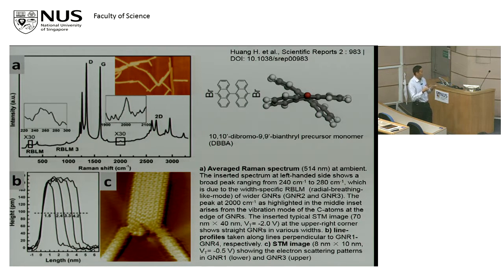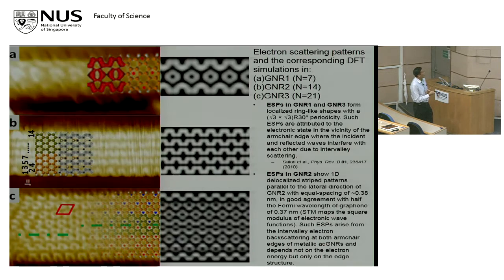But he graduated, he left, so we didn't carry on this work. I couldn't find a PhD student to carry on this work. But it was interesting because you can see that this is an electronic image. You can see interesting images at the edges. We did some work here by simulating the electronic structures of the image. This was done at low temperature, liquid helium, to get the electronic scattering pattern. So this is not an atomic image.